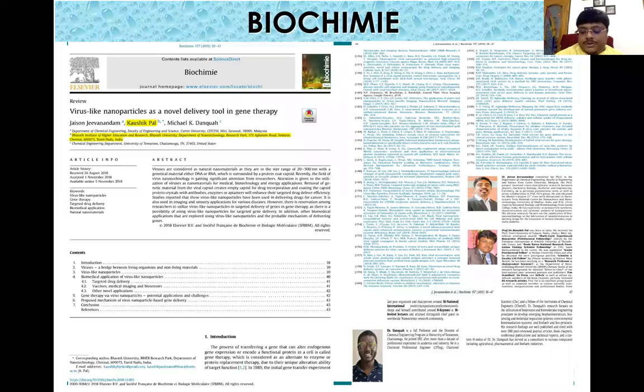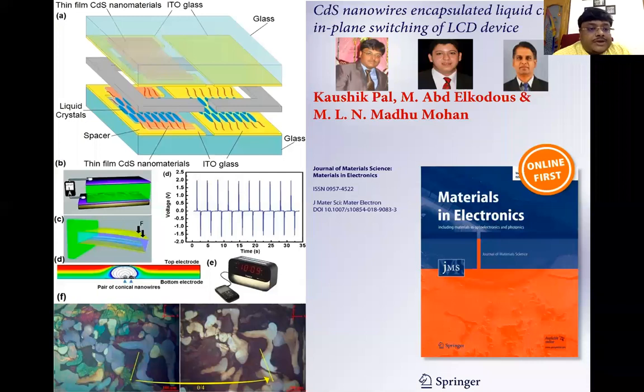high yield nanomaterials. This is the switchable device we implemented, and you can see the several stages we maintain. First, we use the spacer, then liquid crystal growth, and then we place the CdS nanomaterials and sandwich it. And what happens inside, under the microscope, we will see nice switching. This switching comes only when the nanomaterials and liquid crystals are in the perfect ratio with homogeneous, perfect dispersion. Without this, we cannot get the switchable characteristics. So it is very important to get this.